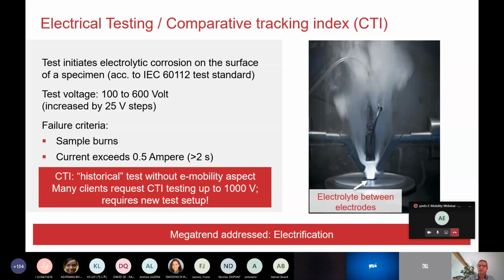You see a very rough picture here on the right-hand side, a lot of smoke around. Basically, these tests operate with two electrodes. You apply a voltage and you create a current flow between the electrodes on the surface of the material. And here the characteristics of the material come into the game: the water take-up of the sample, the conductivity, electrostatics, and things like that. As I said, a historical test designed up to 600 volts.